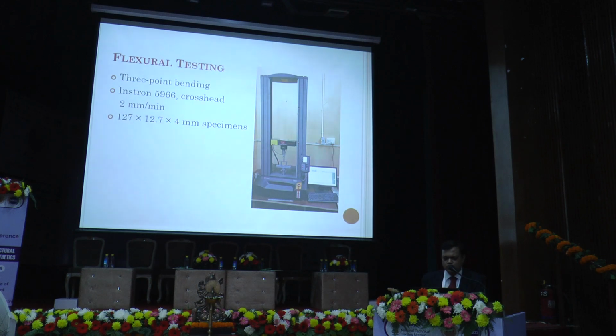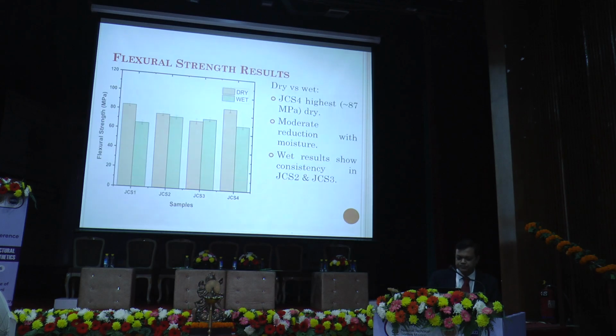Flexural testing was also done with the 3-point bending method and with the same machine, with a crosshead speed of 2 mm per minute. You can see the flexural strength results for both dry and wet conditions, and you can see the dry strength is always better except JCS3. In wet condition, JCS4 has good retention, almost better than all others.